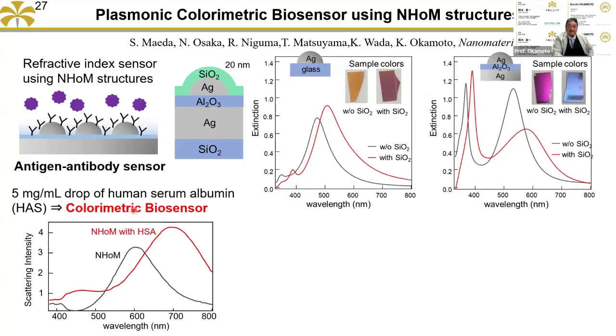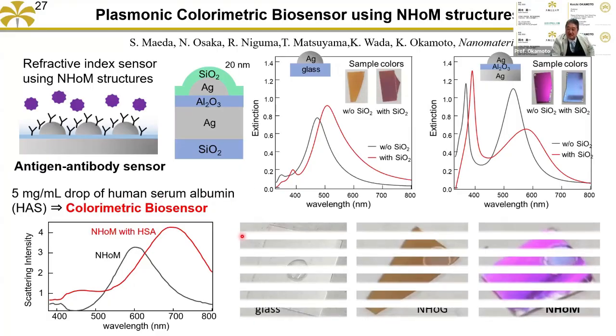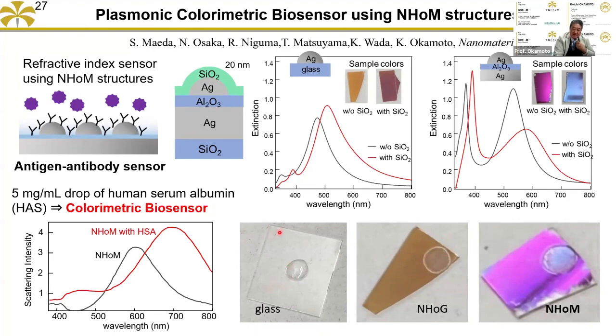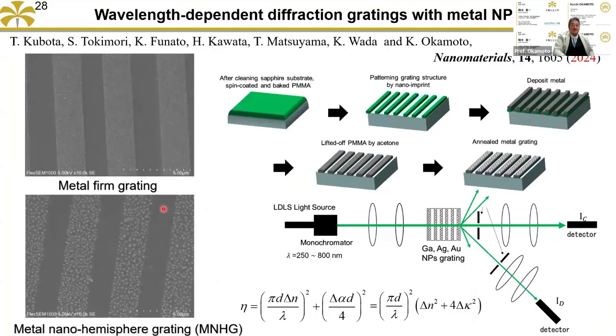Then next we just put human serum albumin on that structure. It's some kind of protein. Then that's the result. By the naked eye, on the glass it's transparent. But on the metal nanoparticle on the glass, the color was not so changed. But with this structure, the initial color is very vivid, shocking pink. And if I drop the protein, the color is changed to blue. So easily you can distinguish the color change. That's why this material is good for colorimetric biosensors.